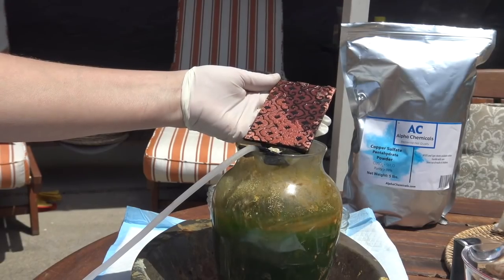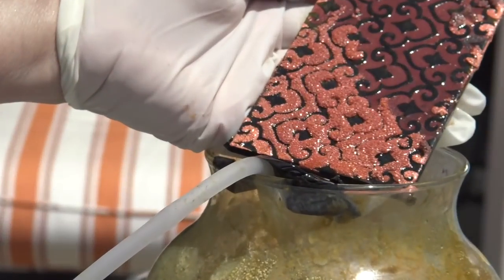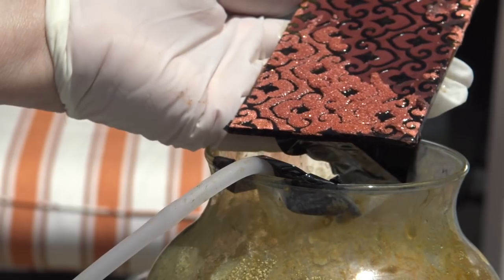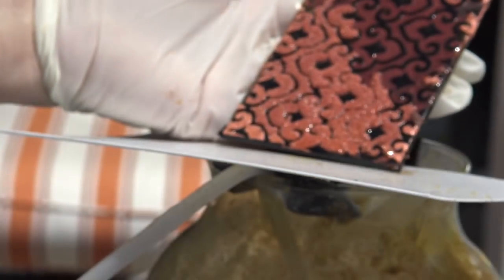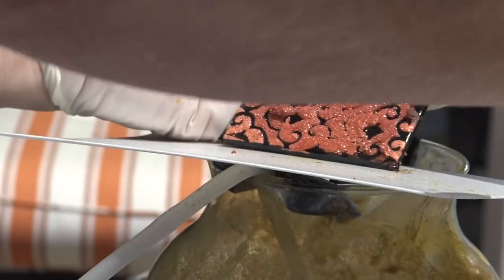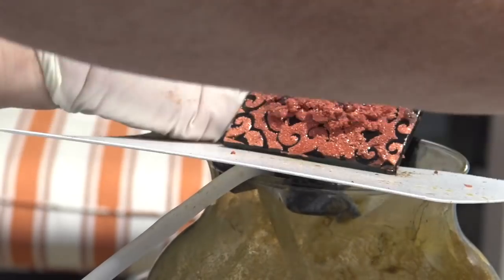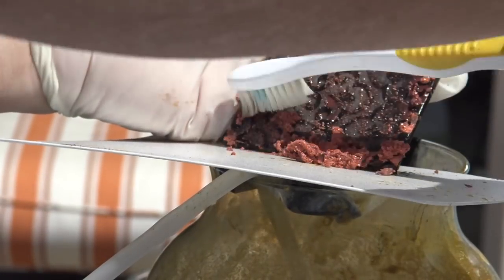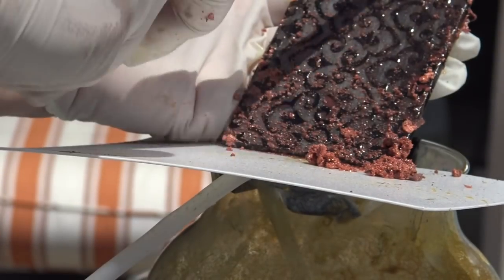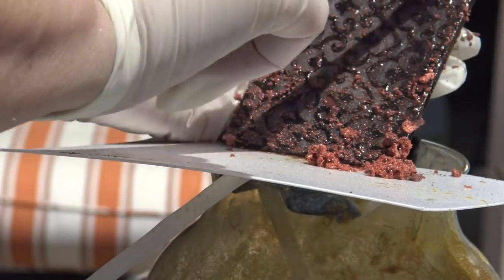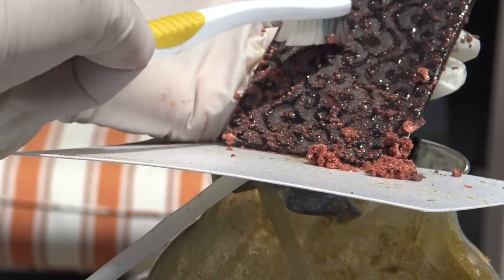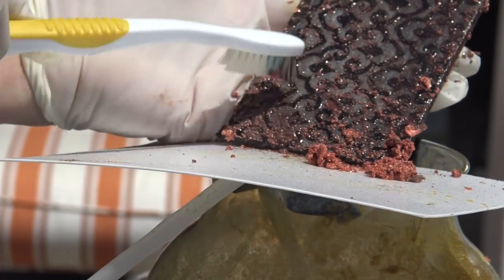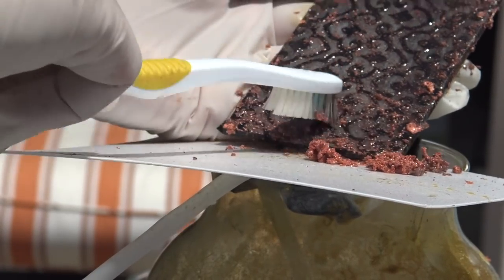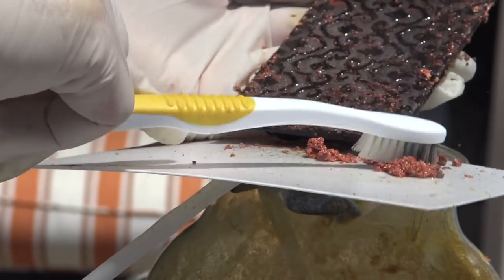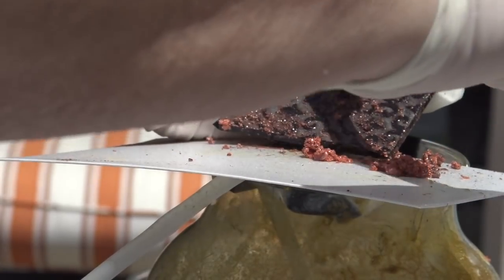So it's been 30 minutes and I pulled my piece out of the solution. You can see this beautiful copper starting to form on the surface. I simply just take a toothbrush or a soft bristle brush and I brush it down onto a piece of paper and just remove it. Just make sure you're using a soft brush because you don't want to rip off your resist. After I get all of that removed, I simply put it back into the solution and let it sit for an additional 30 minutes.